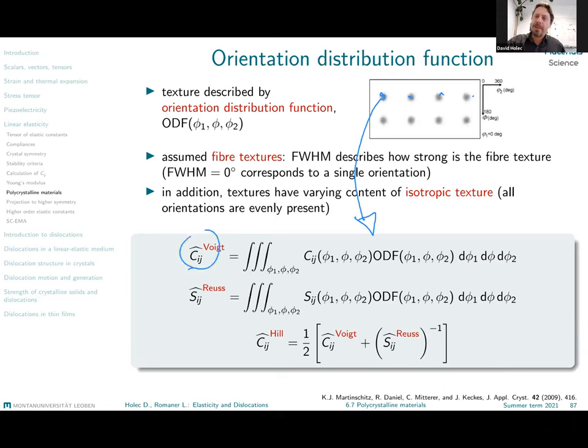For the Voigt and Reuss estimates, from the fact that either I have uniform stress or uniform strain, here I have the uniform strain and here I have the uniform stress. From those facts, I'm then averaging either elastic constants or elastic compliances. The Hill average is once again simply the mean value of the Voigt and Reuss limits.